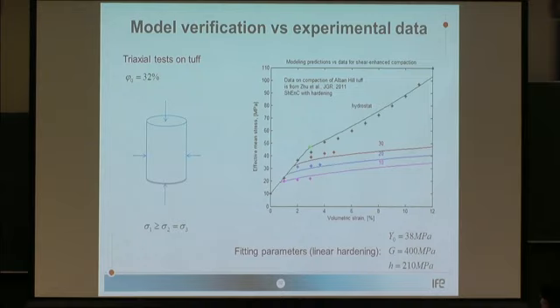So this is how they look for the case of limestone, and this is another example, a triaxial test on tuff. And tuff is a slightly tougher case, because it has 32% porosity. So theoretically, our models with a single sphere should not work on it. Because everybody from homogenization theory would say, yeah, but we have interaction between the pores and things like that. And yet the simple model of a cylindrical pore, where we just take essential physics into account, and by essential physics I mean elastic and plastic pore collapse around the pore, is able to capture the behavior of experimental curves. Yes, we have a slight disagreement here, but still the general trend is reproduced pretty well.